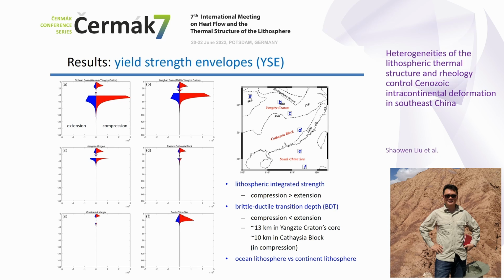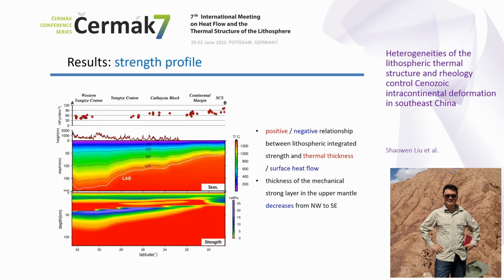The BDT depth is around 13 km in the Yangtze Craton's core, while it decreases to 10 km in the Cathaysia Block in compressional condition. In addition, the lithosphere in the ocean and continent shows a big difference. Here, we show the strength profile from the western Yangtze Craton to the northern South China Sea. We found that the lithospheric integrated strength has a positive relationship with the thermal thickness, but a negative relationship with the surface heat flow. The thickness of the mechanically strong layer in the upper mantle decreases from northwest to southeast and almost disappears in the northern South China Sea.